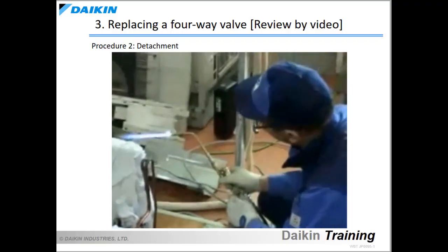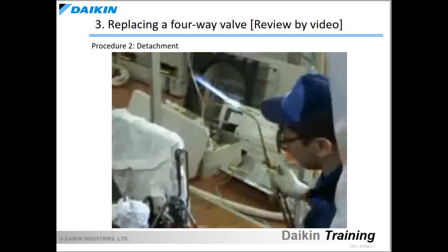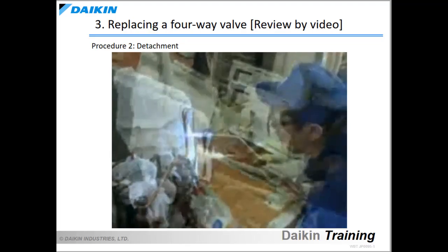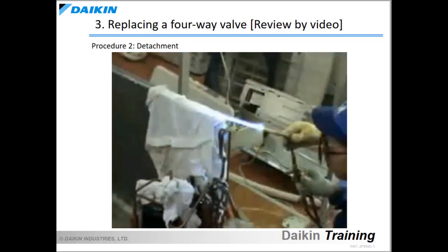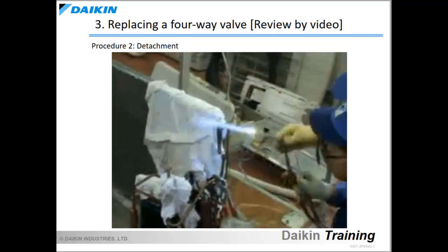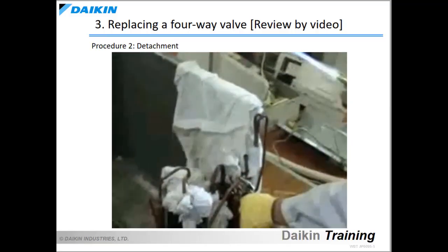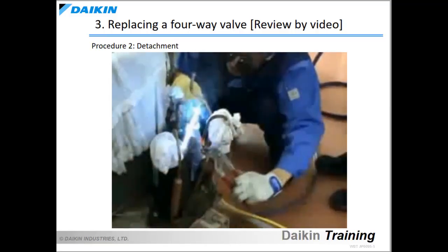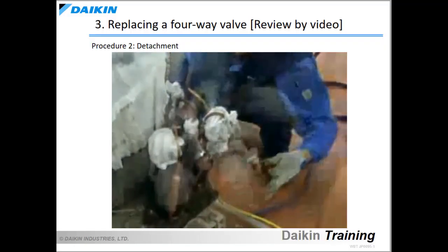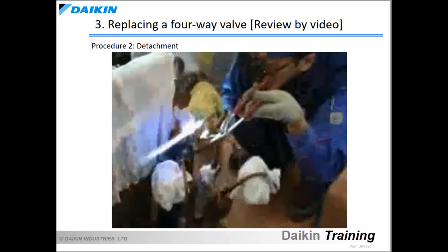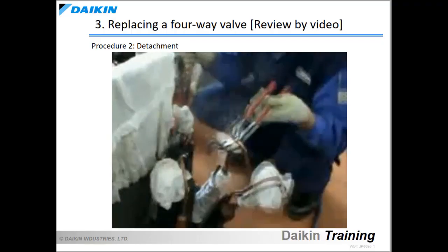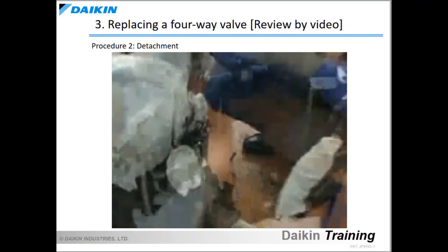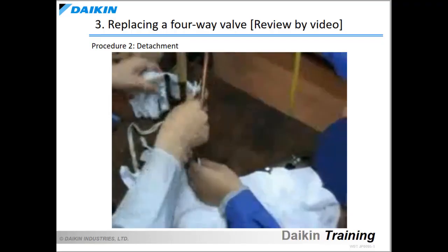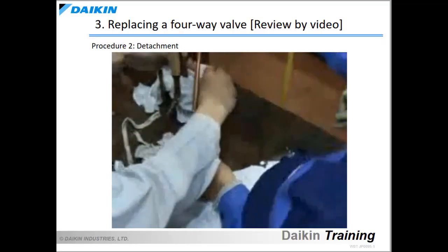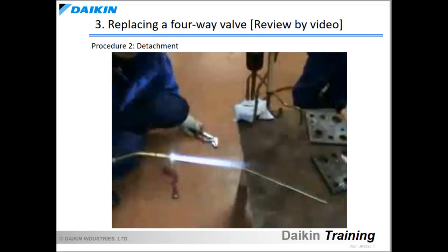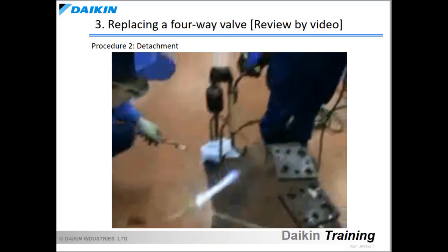Perform nitrogen replacement by injecting nitrogen into the piping to be removed. The 4-way valve's internal valve is made of resin and melts at approximately 250 degrees Fahrenheit. If the valve melts, it will affect its movement, so protect it to prevent the valve temperature from exceeding the melting point. If the flame is applied in the same direction as the 3 ports of the 4-way valve, the pipe behind them will also be heated, possibly causing a hole. So, be sure to apply the flame on the target pipe at a 90-degree angle.